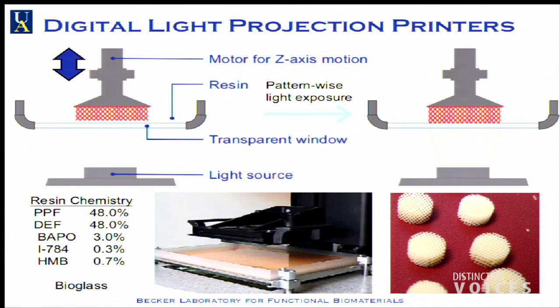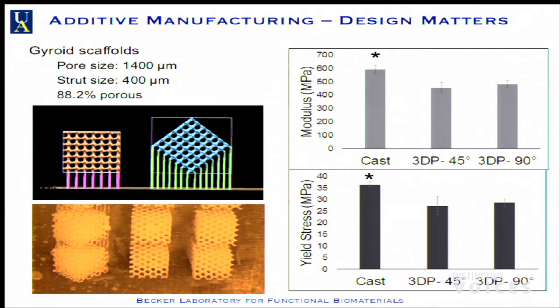Now, one of the other things, and I'll show you this slide because it points out some of the challenges. Because it's a layer-by-layer process, it's inherently weak in one direction. There are some really exotic things going on in South San Francisco with a company called Carbon. You might have seen this, where they're solving this problem with a continuous liquid interface process. They have some resolution images, but I think that's one of the big challenges that's now been overcome. If you print at 90 degrees or 45 degrees, either print geometry is fine. You can see that they're on average 25 to 30% weaker than the bulk material. But you can compensate for that if you can control degradation. And that's the point I want to make.